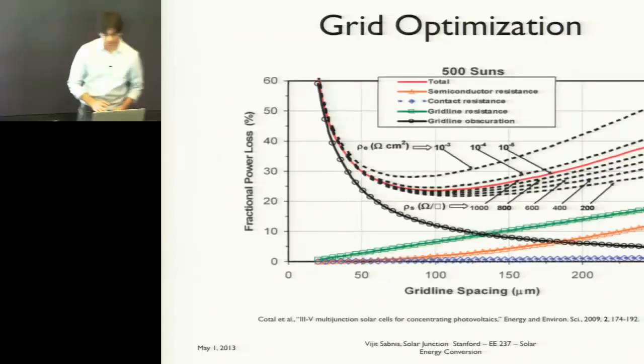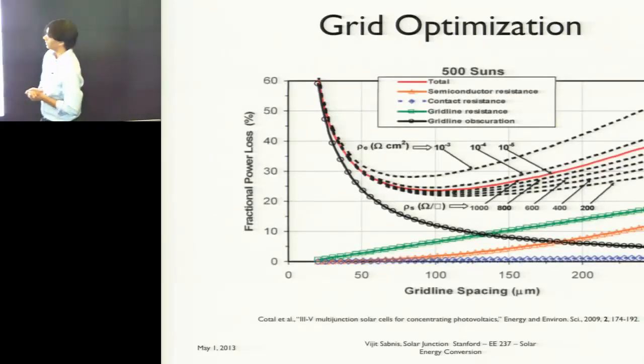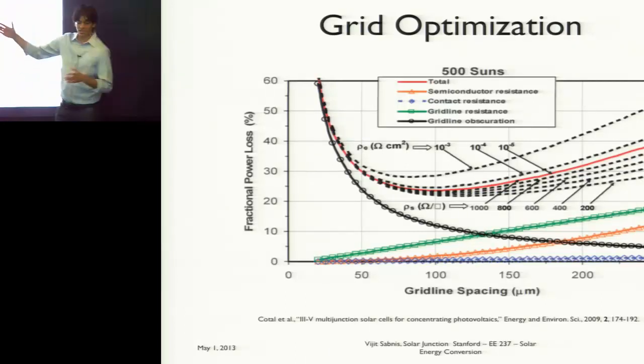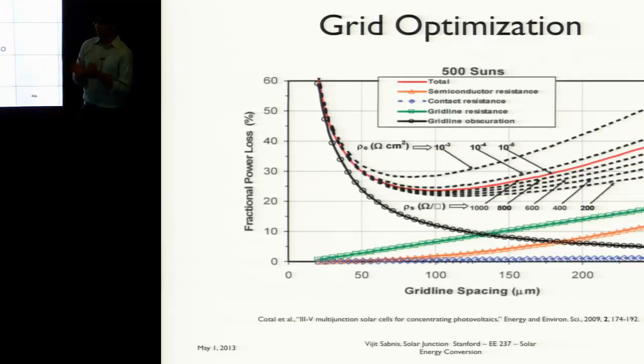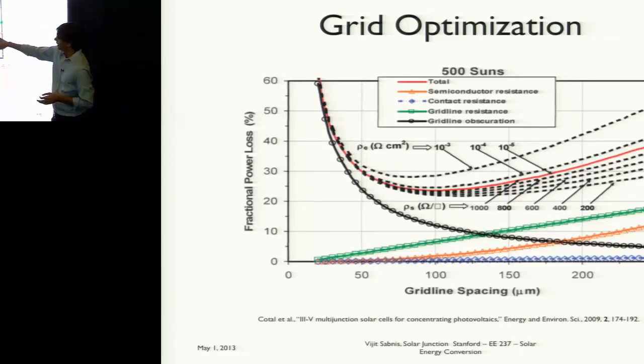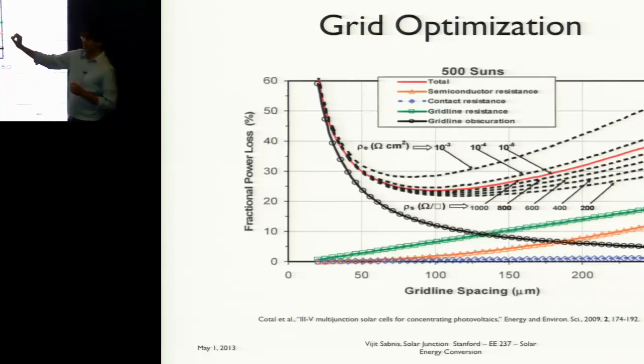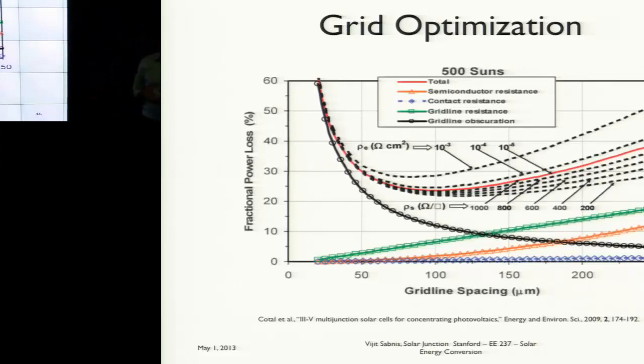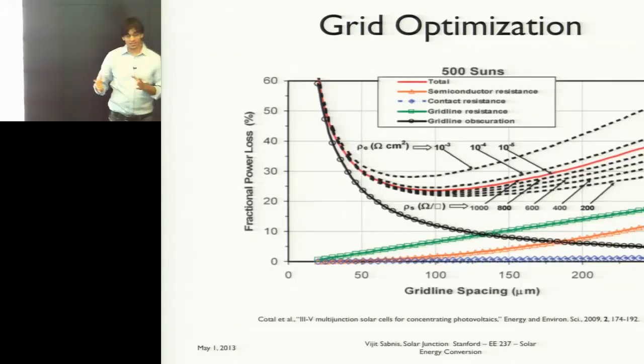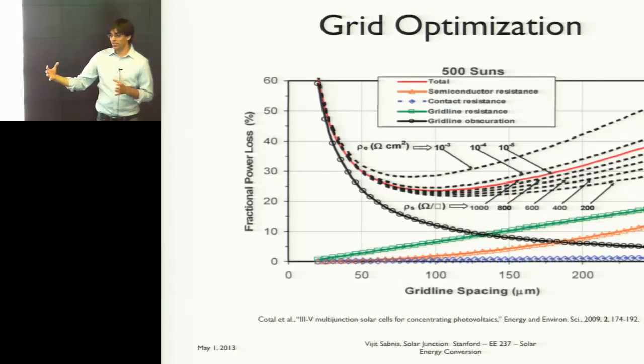And when you look at adding these different components together, this black line is your shadowing loss. As you get to smaller grid spacing, you have more shadowing within your solar cell. And then the blue line is your contact resistance, your orange is your emitter resistance, and the green is your grid line electrical resistance. If you sum all of these together for a particular concentration, you'll find there's an optimal grid line spacing when you design your solar cells of about 100 microns. So most CPV multi-junction solar cells have a grid spacing that is much narrower than what you'll find in a traditional flat plate solar cell.